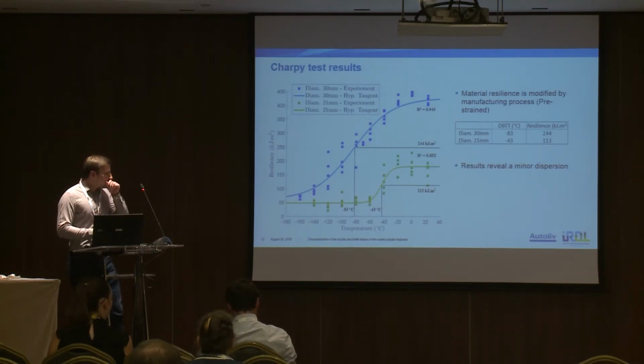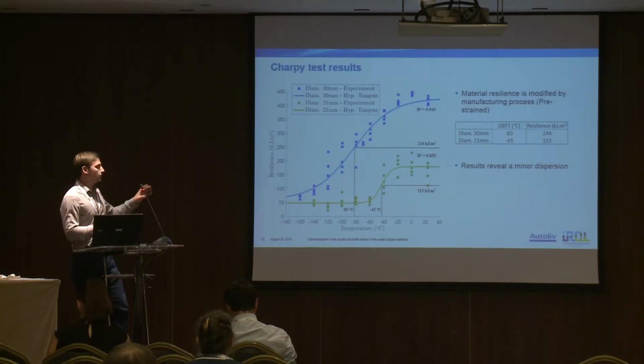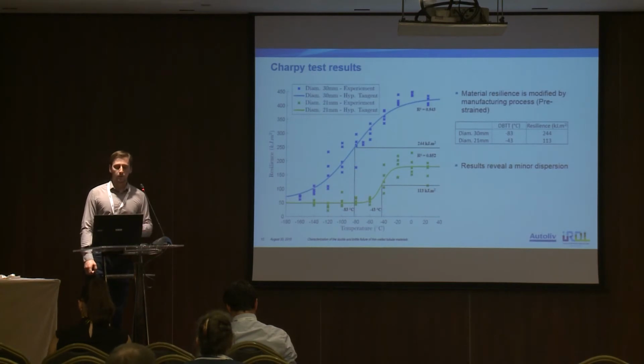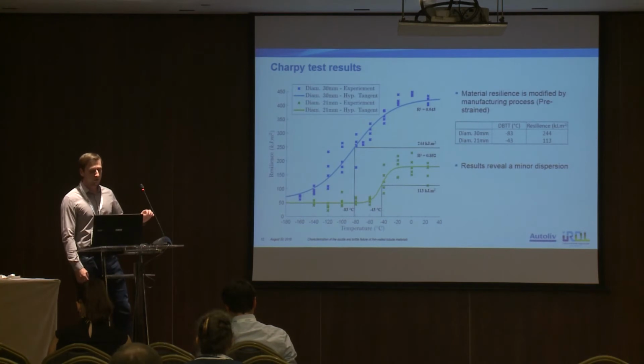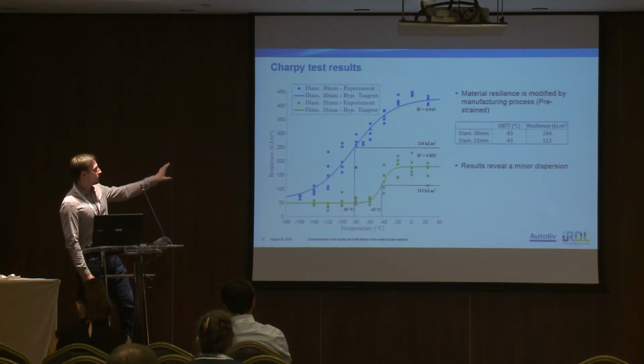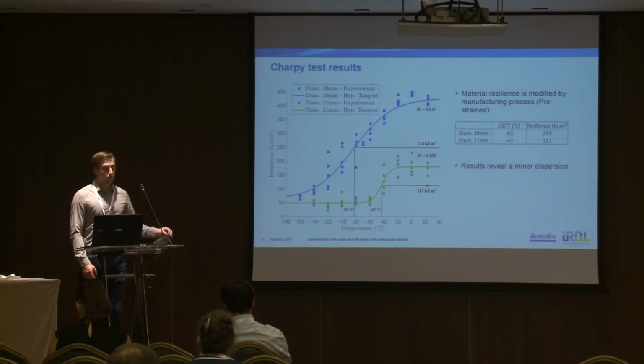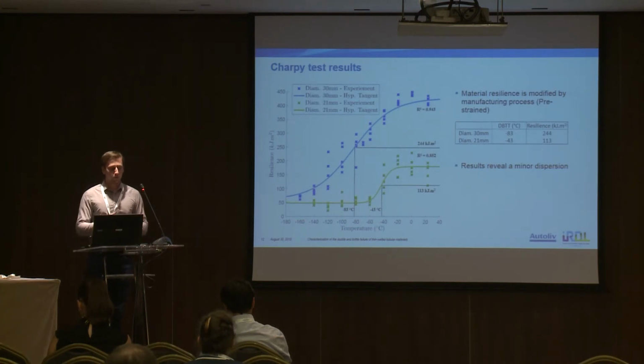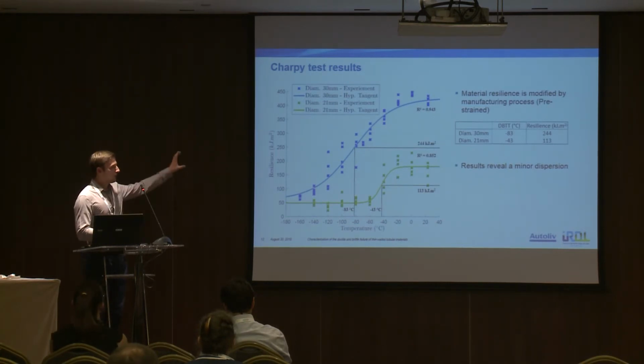So, of course, it's really hard to compare these results, but there is one important fact about the resilience at room temperature. As you can see, resilience is divided by more than 2. So, between the 2 materials, which are initially in exactly the same state, there is a very large gap. So, we try to explain why there is this gap.